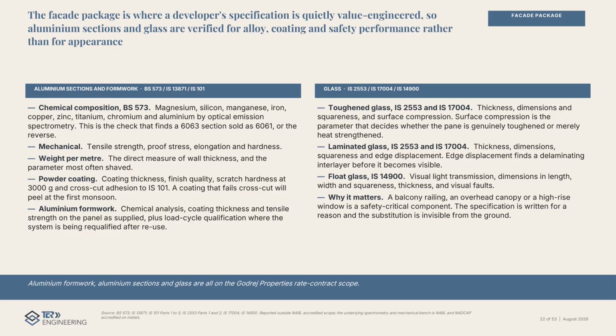The facade package is where a developer's specification is quietly value engineered. So aluminium sections and glass are verified for alloy, coating, and safety performance rather than for appearance. On aluminium, we run the full chemical composition by optical emission spectrometry, which is the check that finds a 6063 section sold as 6061. Then tensile, hardness, weight per meter, powder coating thickness, scratch hardness, and cross-cut adhesion. On glass, we measure surface compression on toughened panes, which is what separates genuinely toughened glass from heat-strengthened glass, and edge displacement on laminated panes.